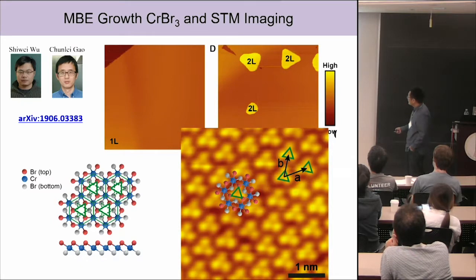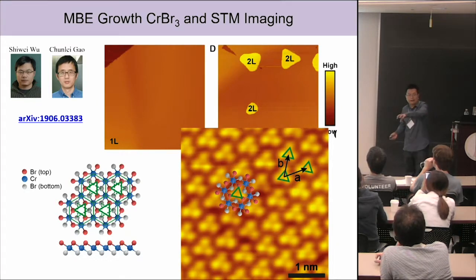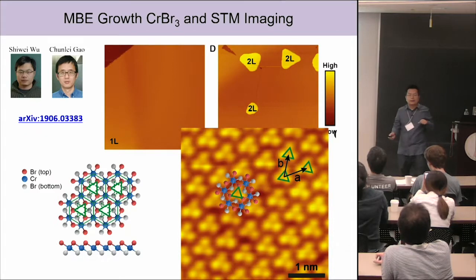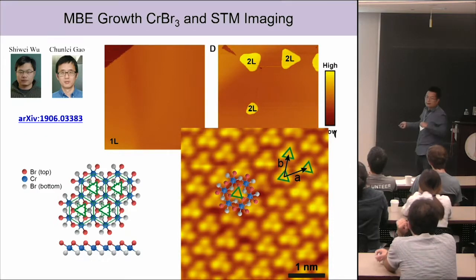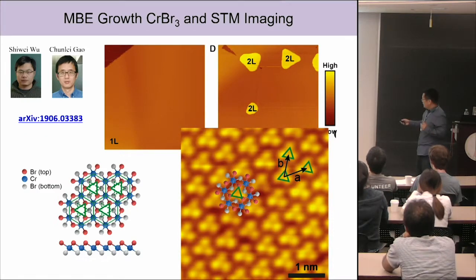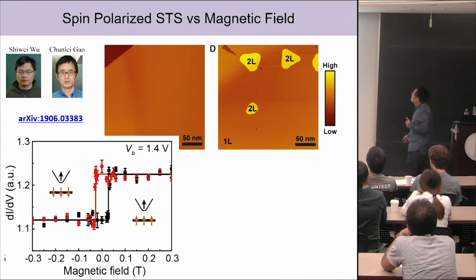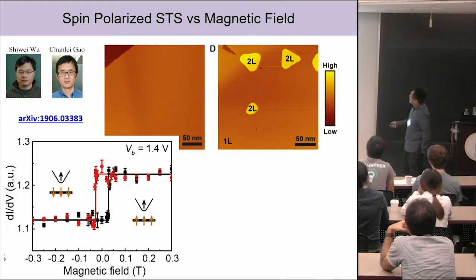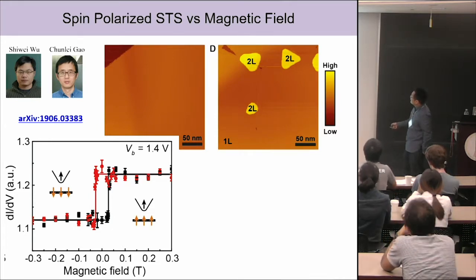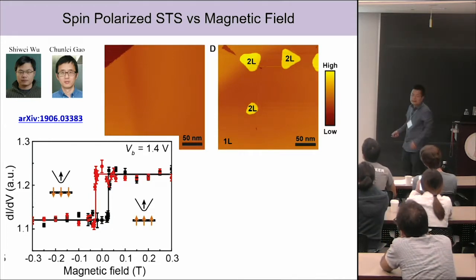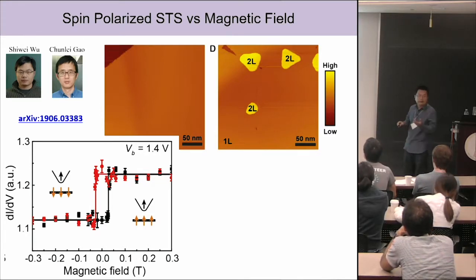Each of these triangles has 3 atoms here. These triangles correspond to the 3 bromide atoms on top, as I taught you at the beginning, right? These triangles, okay? Do you follow me on this part? Then you can do spin-polarized STS or STM measurements, and then you can see this hysteresis, right? So it means it's a ferromagnet in the monolayer. It's not a surprise.